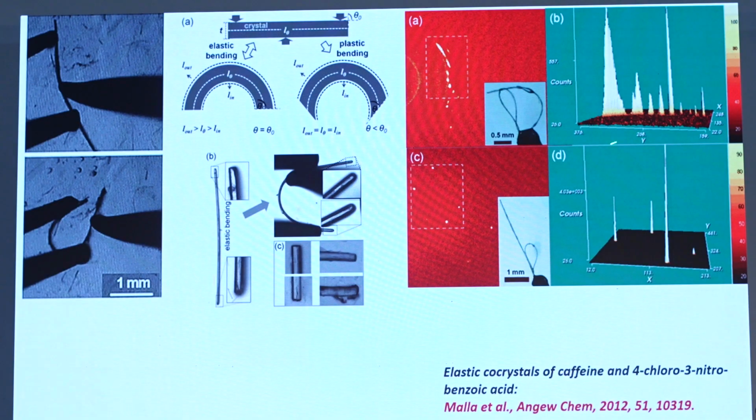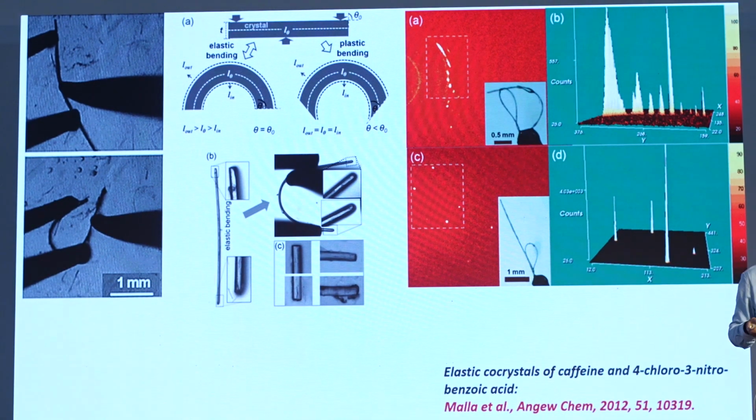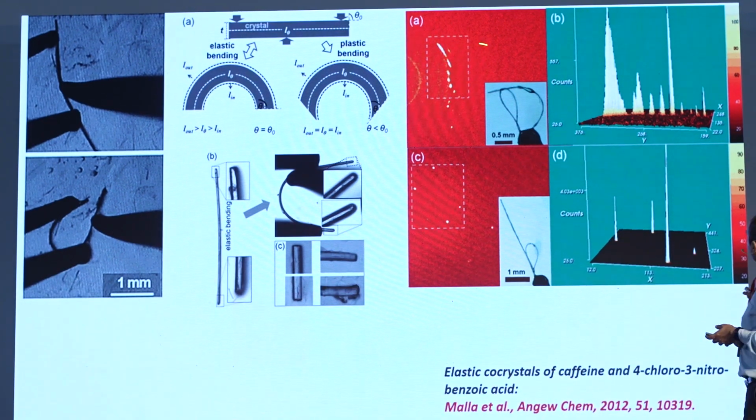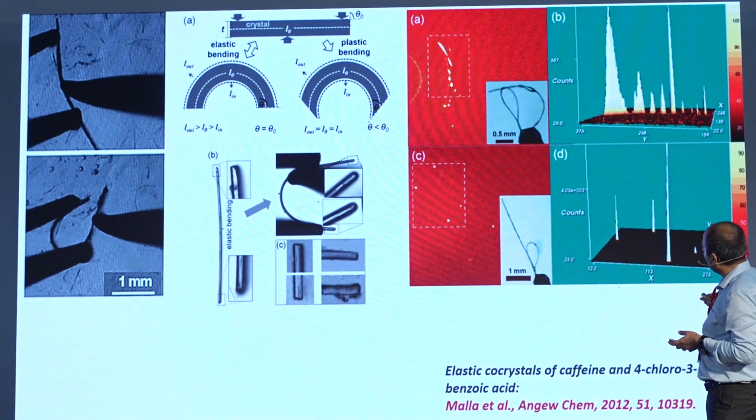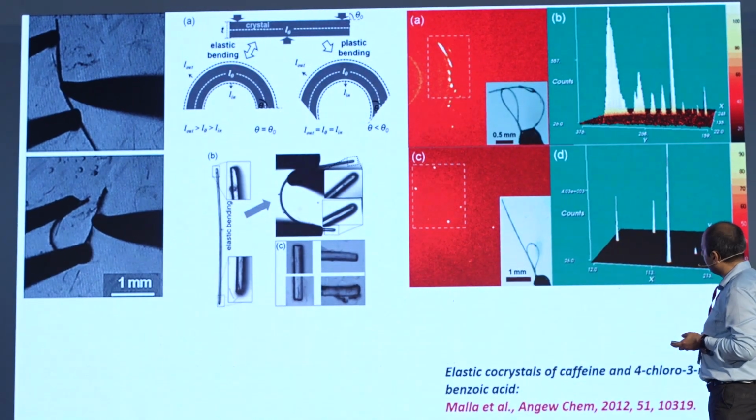You will see that the peaks are very, very sharp, and here you see that there is diffuseness, there are streaks, and therefore the peaks tend to get broadened. But again it comes back to the initial configuration, you restore the crystallinity of the material. So that tells you there is some kind of mosaicity or spread, there is broadness of peaks when you bend the crystal in the bent region compared to that of the unbent region.